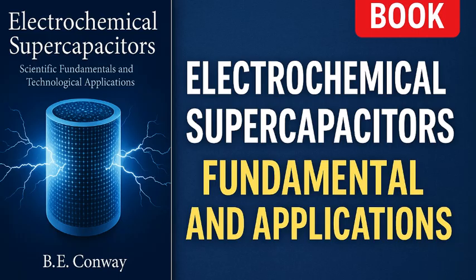For example, quinone hydroquinone redox couples on carbon surfaces can store charge by reversible reaction, like a tiny battery on the surface. This can boost the capacitance beyond the purely electrostatic double layer value, which sounds great, and indeed it can contribute some extra capacitance. However, if those groups undergo redox, they can also lead to drift in voltage or capacity fading after many cycles if the reactions aren't perfectly reversible.